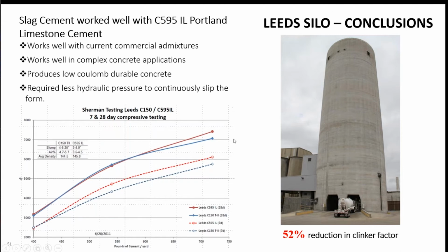Something that's of interest as we talk about sustainability is that reduction in clinker factor. So on this particular project, there was a 52% reduction in clinker factor, which was a combination of using the type 1L cement and the slag cement actually allowed a clinker reduction. So this was a very environmentally sustainable mix that actually had outstanding performance in excess of what would have been achieved with just a type 1 cement.